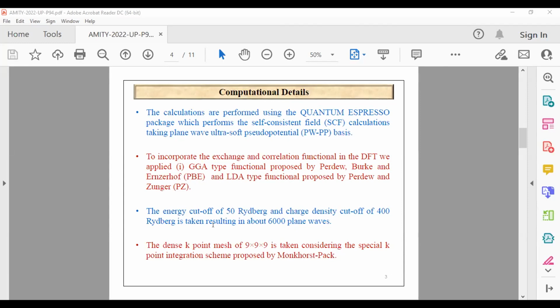To incorporate the exchange and correlation functional in density functional theory, we used the generalized gradient approximation proposed by Perdew, Burke, and Ernzerhof, and the local density approximation type functional proposed by Perdew and Zunger. So we basically took 2 different kinds of functional. One is GGA and another is LDA. In the plane wave calculation, an energy cutoff of 50 Rydberg is taken, and a charge density cutoff of 400 Rydberg is taken. And a K point mesh of 9 by 9 by 9 is taken, considering the Monkhorst-Pack scheme of K point sampling.